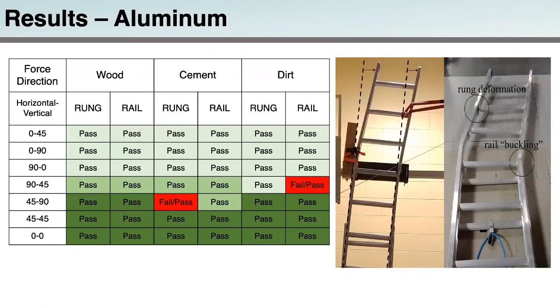Both failure occurrences produced buckling of the aluminum side rails beyond regular deformation observed in the other trials, and some degree of rung deformation or pullout from the side rails. So you can see here, this is an aluminum ladder, and this is the deformation in the ladder. So these dotted lines kind of represent how the ladder should be sitting, and you can see that it's significantly bent off to the right.